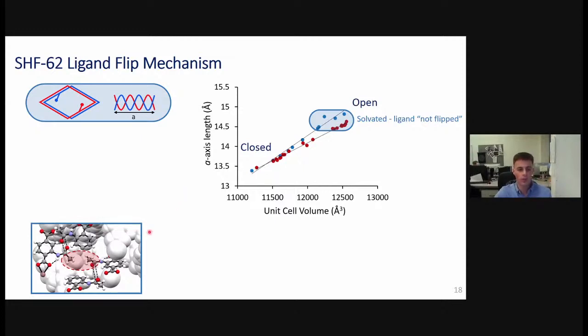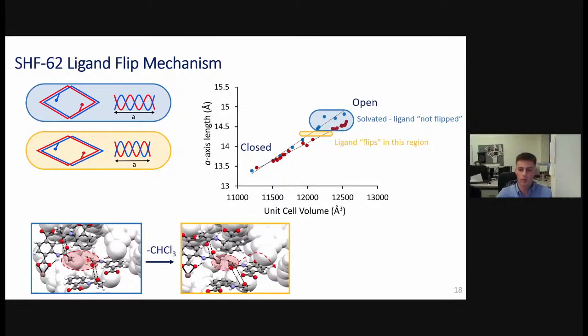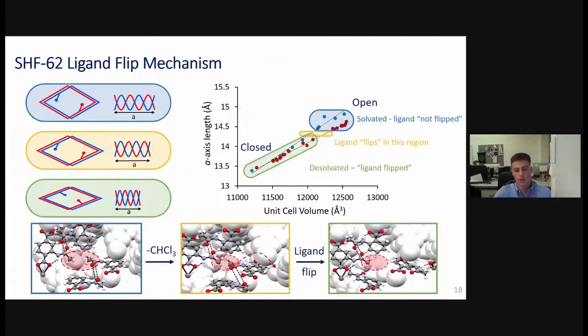So if we look more closely at the crystal structure, we start in our solvated phase with chloroform. And we see these two methyl groups on adjacent networks, and they're pointing towards each other, but they're far enough apart that they can coexist quite happily. But as we gradually remove some of our chloroform, what happens is the A-axis contracts, we move along here, and that brings those two methyl groups closer together to a point where they're too close to coexist. And what happens is that contraction of the A-axis forces 50% of these ligands to rotate out of that plane to avoid this unfavorable steric clash.